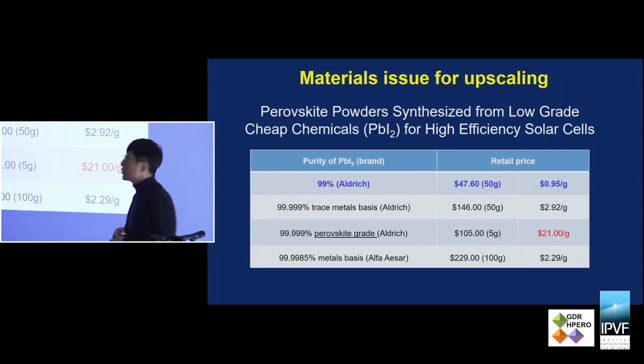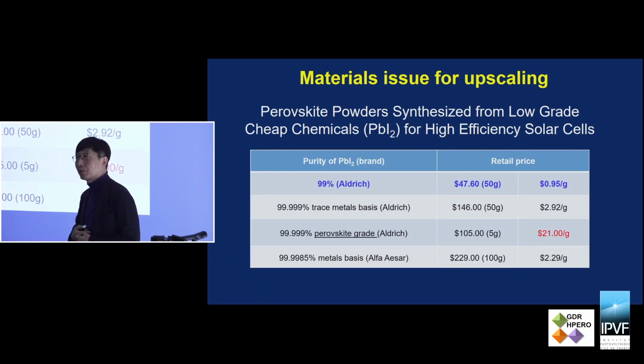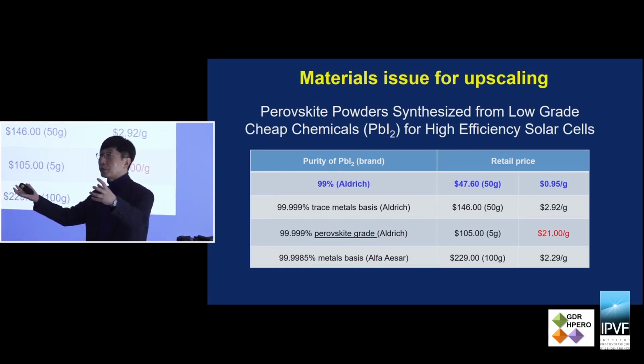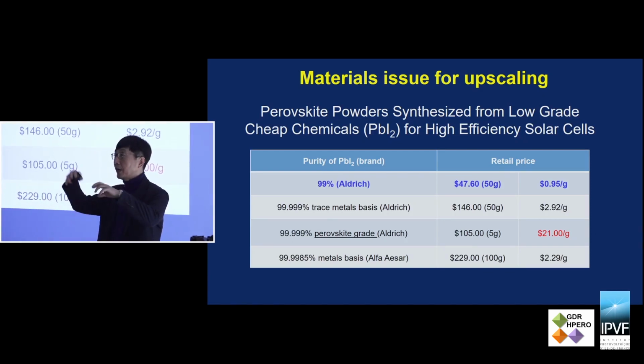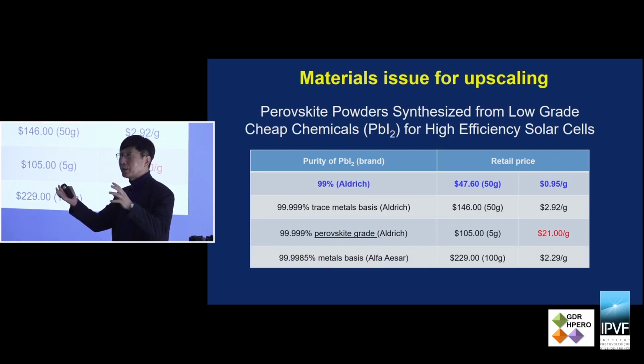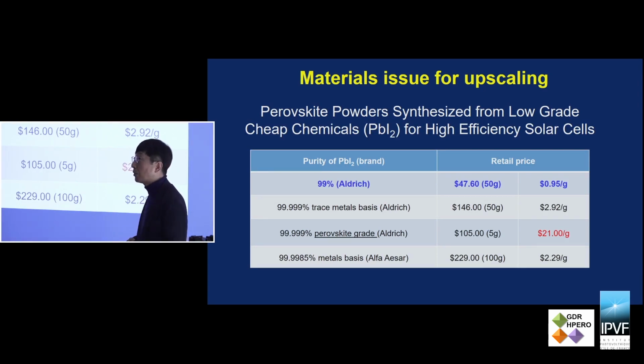And finally, I'd like to mention the material issue. Material is very important. For instance, conventionally we use precursor materials such as FAI and PbI2. When you compare the high-grade PbI2 and the low-grade PbI2, you need high-grade PbI2 to make high efficiency. We still don't know exactly what is going on with the low-grade PbI2, but probably impurities play an important role in creating defects. But also this high-grade PbI2 is very expensive, so it is not suitable for commercialization.